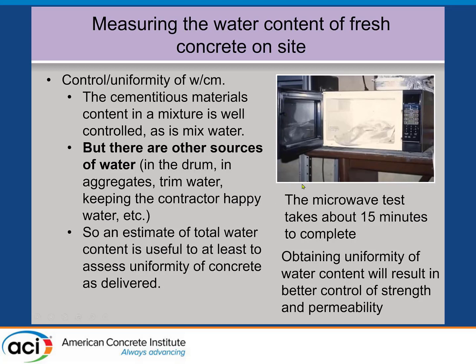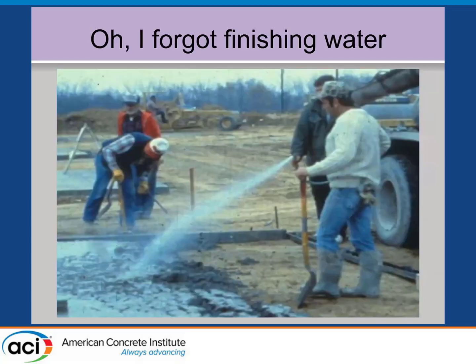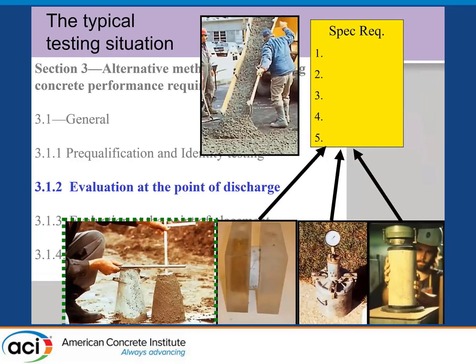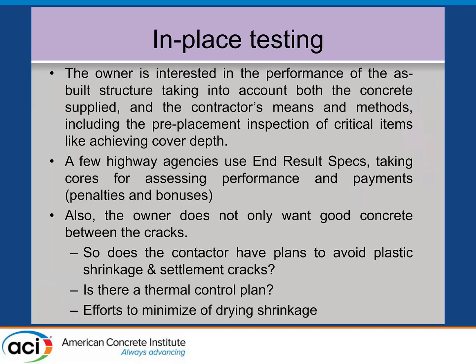So uniformity is important. You don't want different loads arriving with different water contents. And I forgot about finishing water. Fine example of adding water on site as the concrete gets away from them. But typically we measure slump and air on site. We might measure rapid chloride permeability, and we measure strength, make cylinders. But the owner wants in-place tests, as I mentioned.